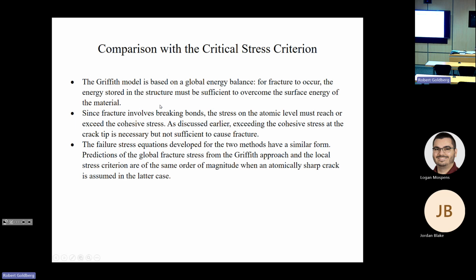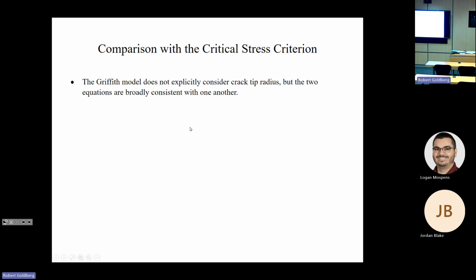But the truth is, whether we do it by a stress approach or an energy approach, as I mentioned earlier, fracture still involves breaking atomic bonds. On the atomic level, where everything happens, the stress must reach or exceed the cohesive stress between your atoms. And we talked about how exceeding the cohesive stress at the crack tip is necessary but not sufficient to cause fracture. So the failure stress equations developed for each of these two methods have a similar form, and the predictions of the global fracture stress from these two approaches are of the same order of magnitude when we're talking about a sharp crack. For the case of a sharp crack, the Griffith model doesn't explicitly consider the crack tip radius, but the two equations are broadly consistent with each other.